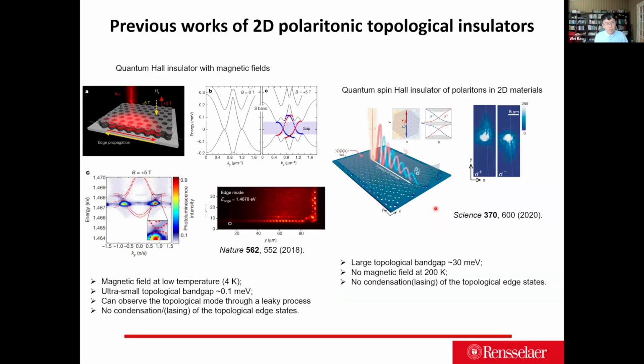There's also a lot of effort to demonstrate the 2D polaritonic topological insulator, done by my colleagues Sven Hofling and Sebastian Klembt. Essentially, they have a quantum Hall insulator, etching gallium arsenide pillars with certain dopants. Because in order to have a Zeeman effect, you need to dope the crystal, eventually you lower the system's quality factor. But on the other hand, you cannot dope the magnetic atoms too heavily. That means the topological protected gap opened in the system is a trade-off with the quality factor. If you want a large gap, you need to dope it a lot, but this sacrifices the quality factor. Because of this trade-off, they don't open up a big band gap.